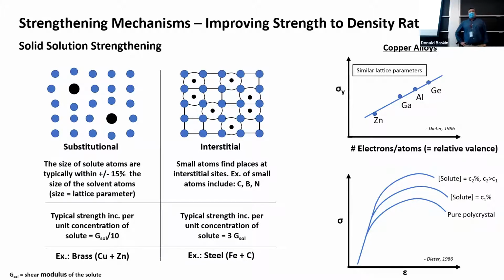There's been studies done on if you have this solvent material and you put in this solute, can you predict whether it's going to sit at a lattice site, or whether it's going to sit in an interstice? There's a lot of modeling that's been done around this, and I think there's some general rules of thumb out there about percentage of the atomic radius. I think the rule says that if the radius of the solute is within 15% of the radius of the solvent atom, then it will sit in a lattice position, a substitutional site. If it's smaller than that, it'll sit in between. So it turns out that when they sit in between the atoms in the interstices, they actually increase strength more than if they occupy a lattice position.